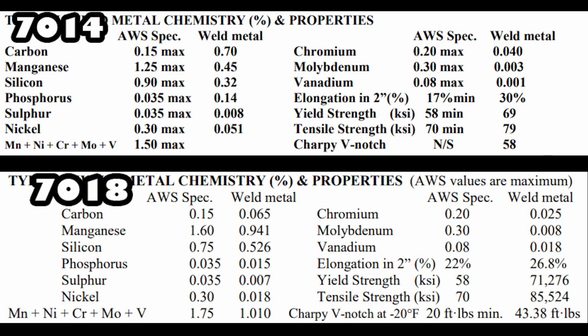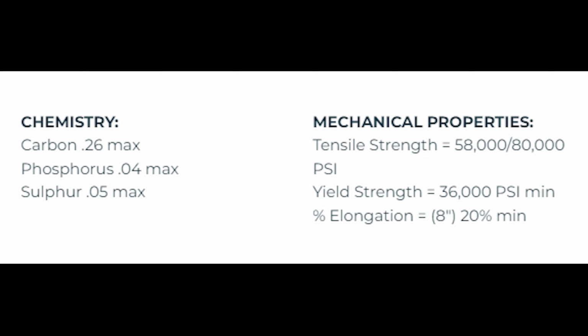Now the Charpy V-notch, there is no spec for 7014, but it tests at 58, which is actually pretty good. However, that's probably at room temperature. The 7018, where it says -20, that's spec'd for the -1 on the 7018-1, and that tests at 43. So again, interesting numbers. Let's look at A36 steel and the specification on that. So here is the steel that I bought from the supplier.